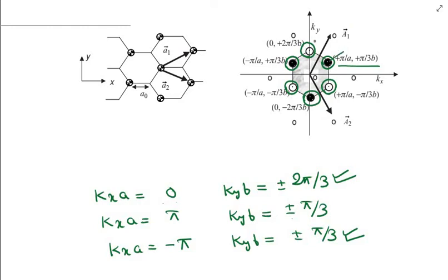There is one hexagonal cell like this over here, and there is another hexagonal cell like this over here. So this point is in total shared by 3 different hexagonal cells. One is this cell, one is this cell, and one is this cell. So 1/3 of this point exactly belongs inside the first Brillouin zone. Similarly, 1/3 of each of these points belongs inside the first Brillouin zone. So in total there are 2 points which basically belong to the first Brillouin zone.